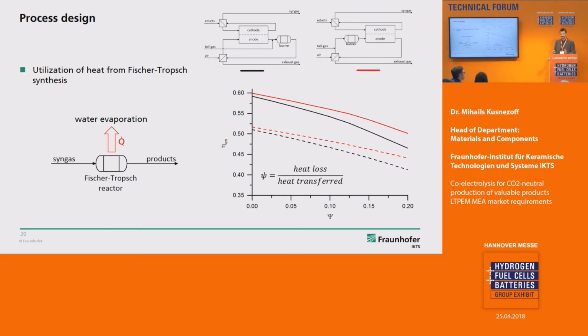Here we again come back to the heat management, because in this system we should have the advantage of using steam, not liquid water. And for this we need heat for evaporating the water. Here you have two examples for using tail gas, which is recycled from the process, because you don't have 100% selective conversion. And you see that the way you recycle it can influence the heat losses in the system. If we assume some realistic heat losses in the system, then you see, depending on how you manage your heat, you can get different overall efficiency, and the red line is the best one, the dark line is a little bit worse.